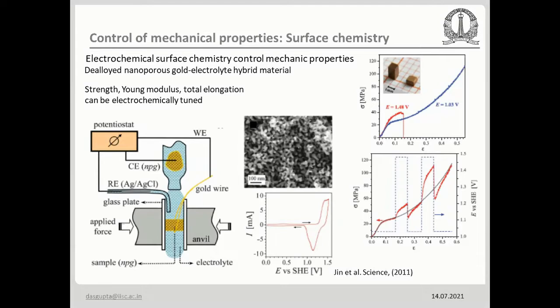It doesn't need to be gold silver, it can be brass. So we can always etch out the less noble material first. This is the idea, that gold is more noble, silver is less noble. So then I can apply a potential such that it only will etch out the silver. And then a self-assembly process goes on. When you do this electrochemical leaching, what you get at the end is a nanoporous material, like it is shown.